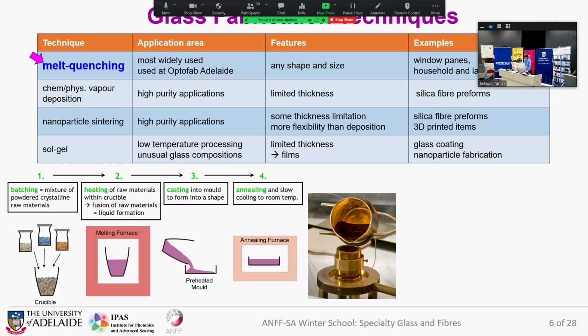So how it works is as follows. You take crystalline raw materials, you mix them according to the recipe, you place the batch into a crucible, the crucible goes into a furnace, you heat it up, and all crystals at some point melt, and crystals that do not melt get dissolved in the hot glass melt. And so at some point, after half an hour or even several hours, then all ingredients are in the molten state.